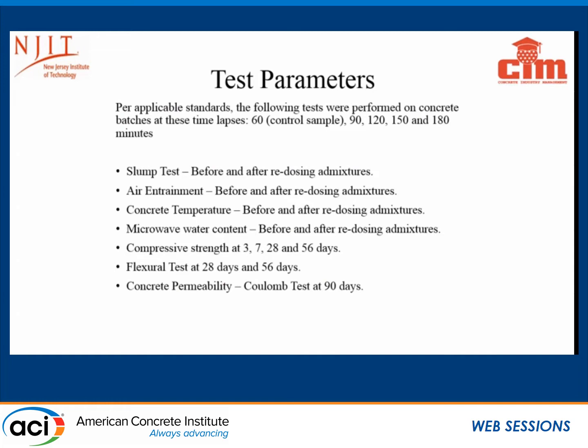These are some of the tests that were done. We decided on timestamps of 60, 90, 120, 150, and 180 minutes to determine the effects and the performance of the concrete at those individual time frames. Typical tests: slump, entrainment, temperature, compressive strength, flexural, permeability. In terms of the tests normally done on fresh concrete, we pretty much incorporated all of them so that we could have an array of results to present.